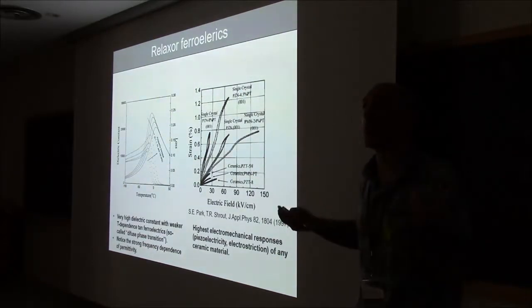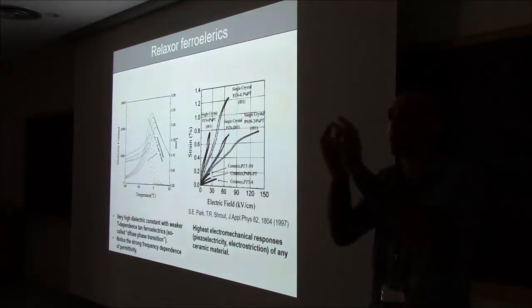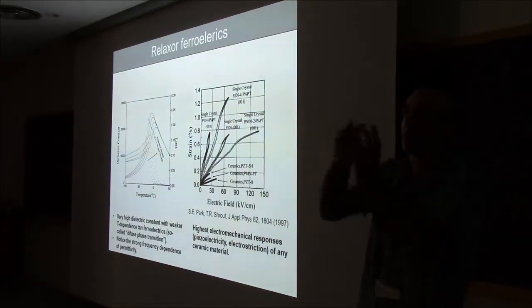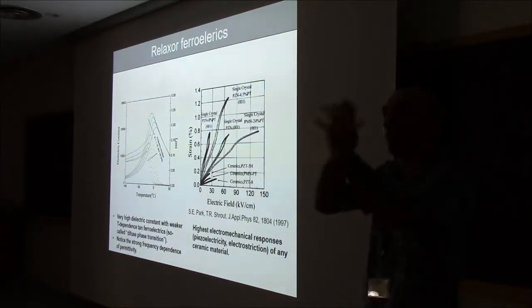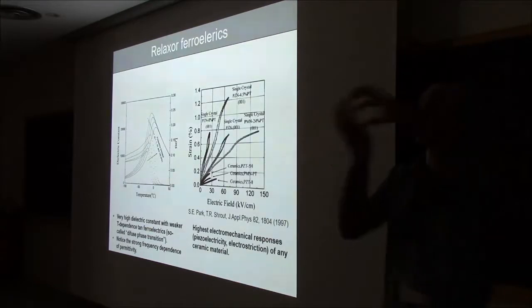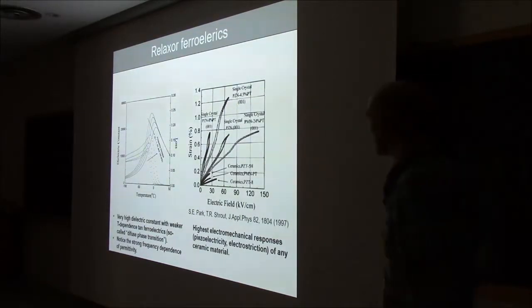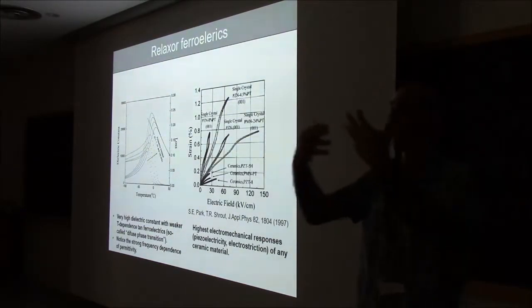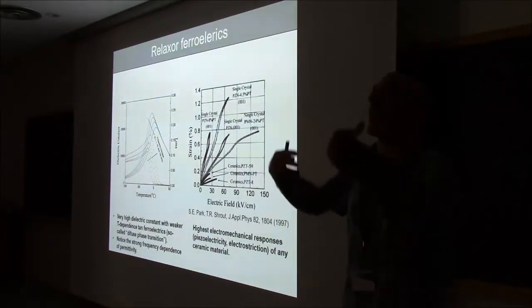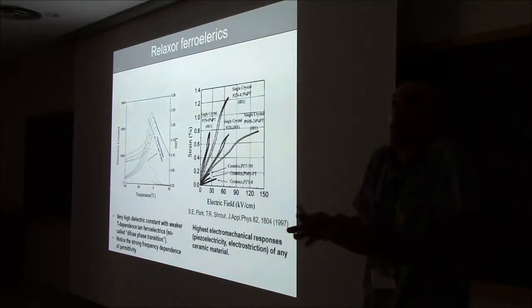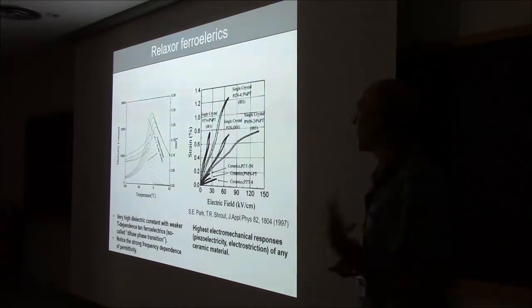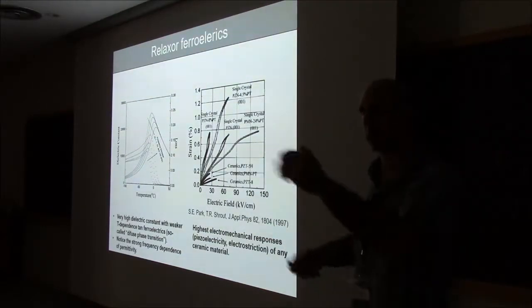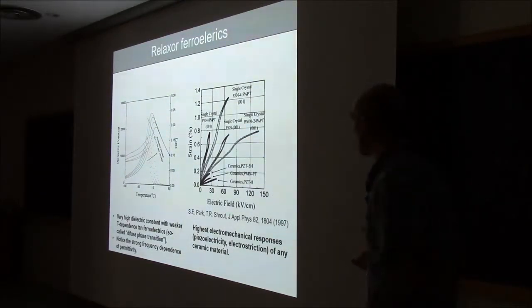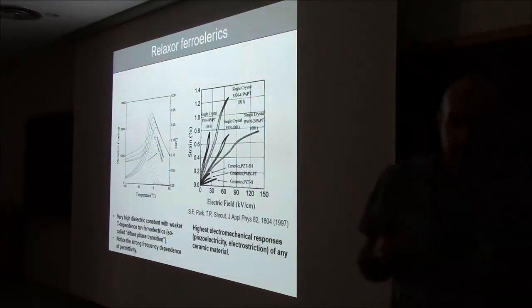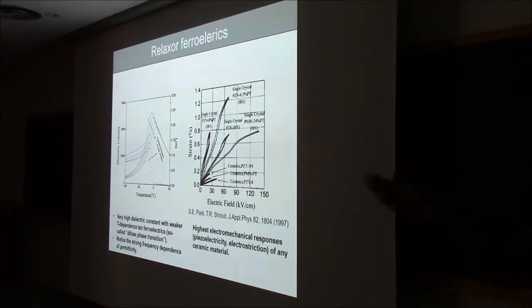For those of you who are into magnetism, perhaps the closest thing is a spin glass. Think of it as a dipolar glass, where you have clusters of polarization that are within that cluster coherently oriented, but from cluster to cluster there is no coherence. These clusters, because it's like a glass, below a certain glass transition, they get frozen, and once they are frozen, then you can induce a permanent polarization. You can apply an electric field and it will stay polarized. These materials are very exciting, or very useful. Well, they are very exciting because the physics is complicated and we like complicated things.